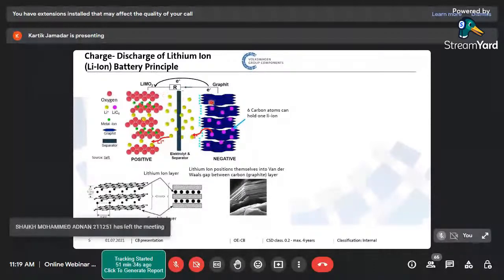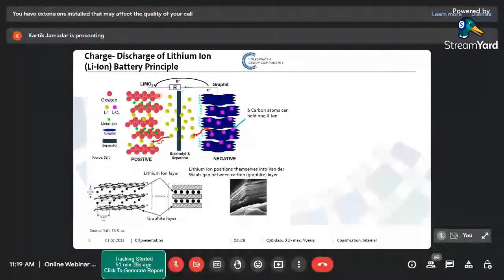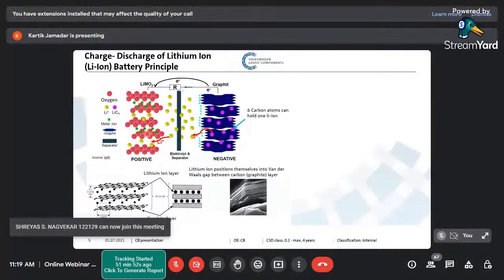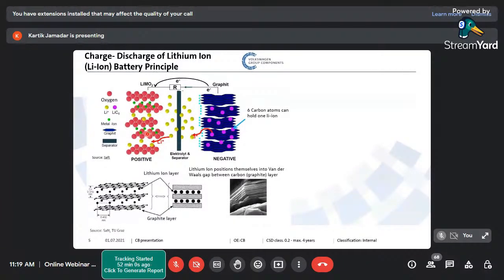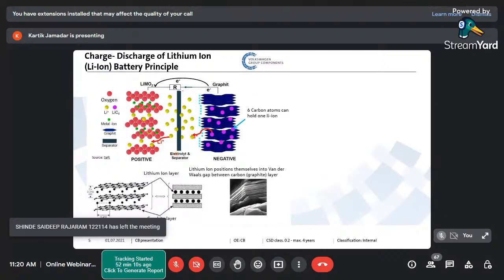So for high power batteries, we use a coating thickness which is practically one fourth the size of the high energy density one. Because of that, everything becomes much closer to each other. The ions have to travel a very small distance, and that's why they can reach the other electrode faster, and because of it, they can release electrons. The same happens when we go from charging to discharge; they also travel a shorter distance. For high energy, as I told you, you need more active materials.